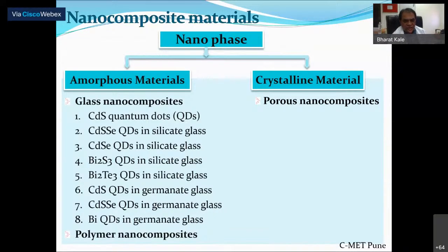As you see, we also have nanoparticles in glasses, very unique things we do. All chalcogenide semiconductors can grow in amorphous materials. Like glass is amorphous. In the amorphous glass, we have crystalline CdS. The important thing here is the 2.5 nanometer to 5 nanometer size, even in bismuth or 11 nanometer size, we can grow in the glass as well as in polymers.